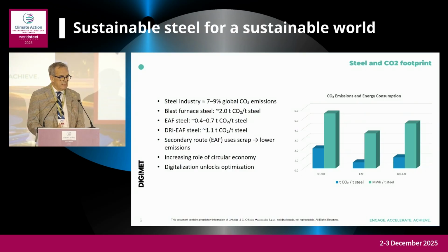However, scrap quality variability can strongly affect melting energy and therefore CO2 emissions. We must always keep in mind that whenever we increase the energy needed to melt, of course we increase the CO2 emissions. So there is a direct relationship between the cost of transformation and CO2 emission itself. The better we understand scrap, the more efficiently we can melt it. That's the reason to invest in digitalization in this area. That is precisely where data and digitalization make the difference.